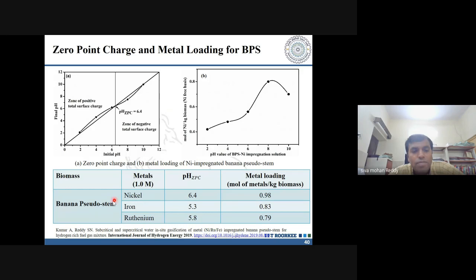So you see that for a banana pseudostem, we have loaded three materials, that is nickel, iron and ruthenium. At the pH ZPC, that is the zero point charge, pH was found to be around 6.4, 5.3, and 5.8, and a metal loading of nearly 0.98 mole of nickel, 0.83 mole of iron, and 0.79 mole of ruthenium has been loaded onto your biomass. Okay.